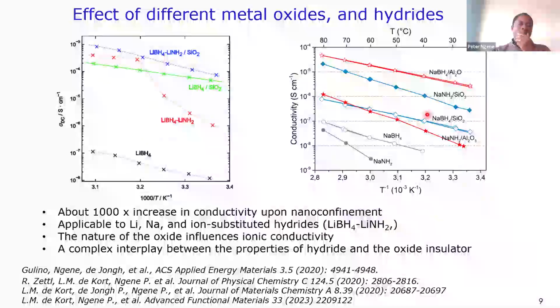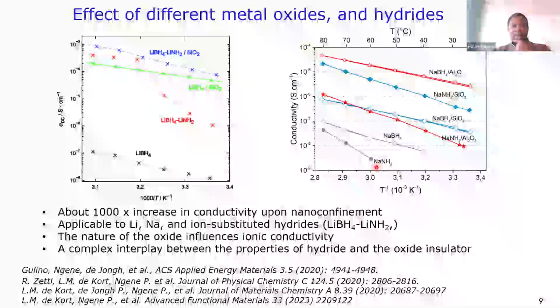And one thing that was also very remarkable is, you can see here different types of material all show this kind of behavior. But one thing I wanted to focus on here is the fact that the nature of the scaffold has a significant impact on this increase in ionic conductivity. This is sodium amide, and this is sodium borohydride.